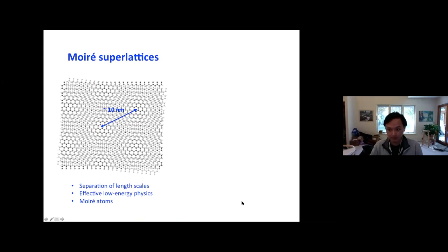I probably don't need much introduction to moiré physics because there were two talks yesterday about this. Just very briefly, when you put two monolayer van der Waals materials, or even multilayers, on top of each other, with either a small twist or the two materials being different, say with different lattice constants, a moiré superlattice structure is formed. Typically the length scale we are interested in is about 10 nanometers. So there is a nice separation of length scale, much longer than the atomic length scale of each individual material. That allows us to separate the low energy physics described by the moiré flat bands in the system, which enhance the interaction effects.